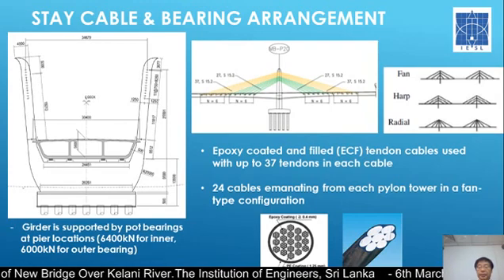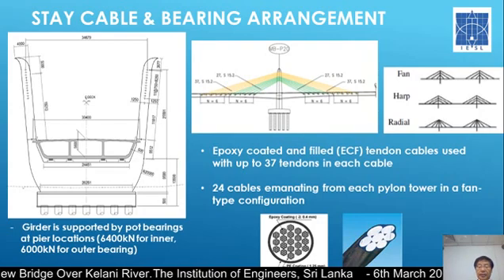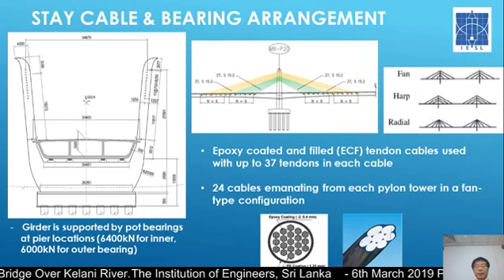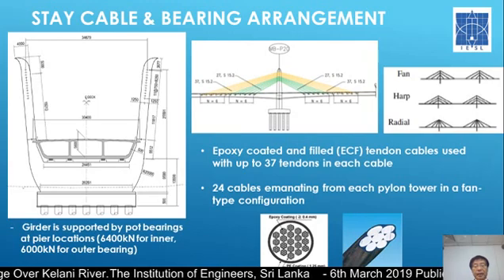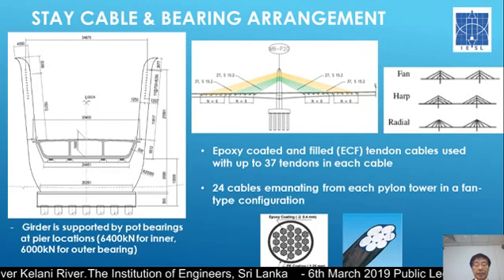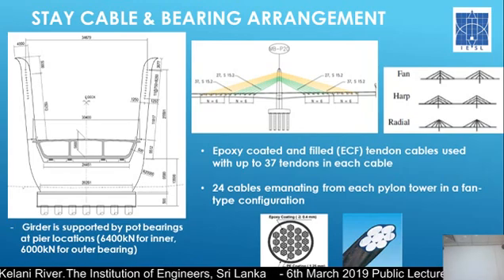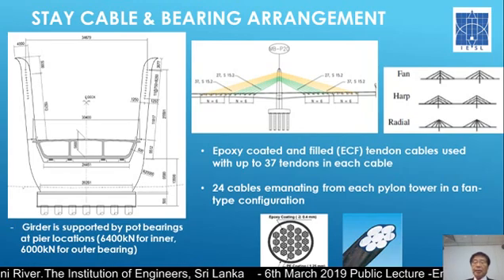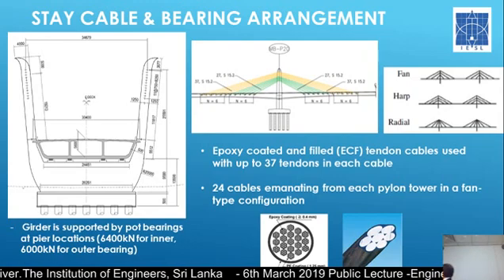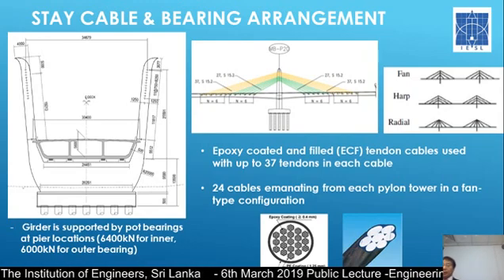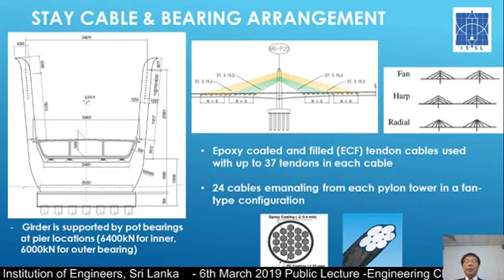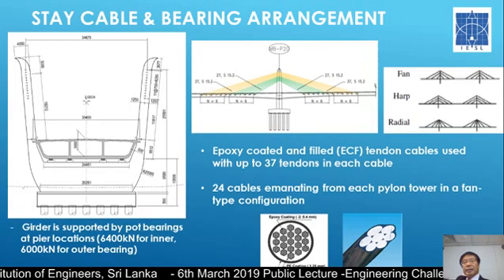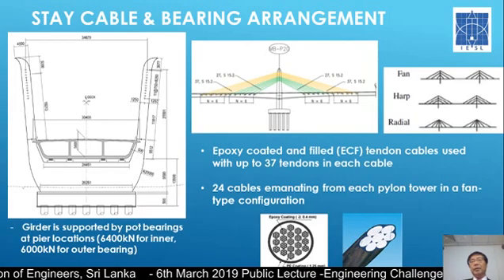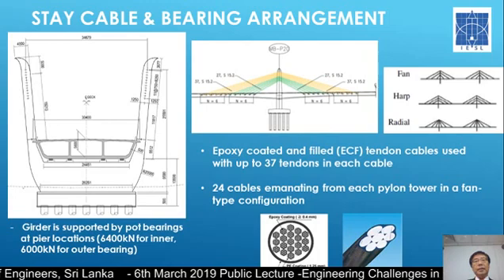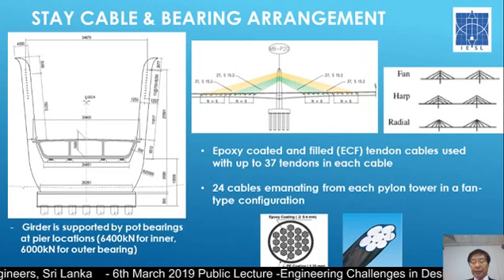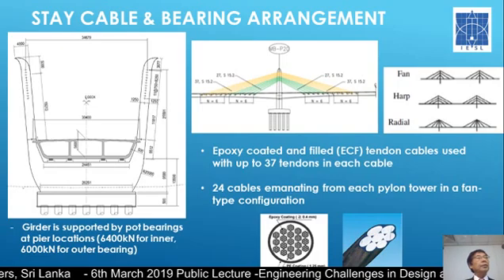As I said, the cable consists of several strands, and the strands are encased by the polyethylene cable. Each strand is what we call epoxy coated and filled (ECF) tendon. So each strand, each wire, is coated with epoxy, and the voids between the wires are also filled with epoxy. So there's no chance of water or moisture coming into this area, so the resistance to corrosion is high.